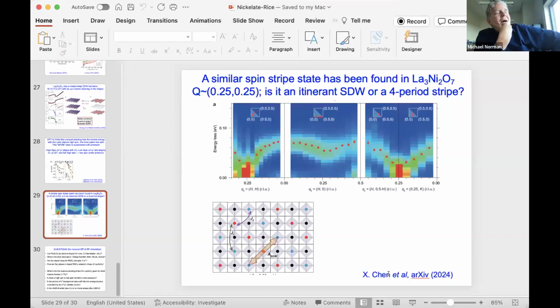Yeah, so this is the point. We're putting a paper on this together, but I've been asking them that we need to have occupation numbers. We'll get them at some point. Of course, one of the problems in band structure calculations is that the charge modulations tend to be weak because the Hartree potential really controls what's going on. It doesn't like to have different charges. The 438 is a good example of that, where we looked at this extensively. It really looks like you have D9, D9, D8 stripes as far as the spin is concerned. But the charge modulation is actually relatively weak, because in DFT calculations, the Hartree potential penalizes you from having a large charge modulation.